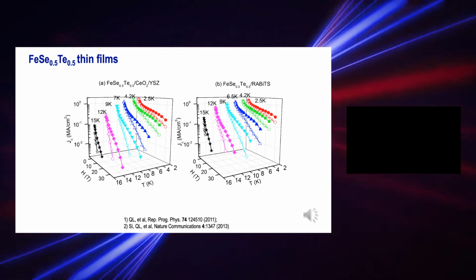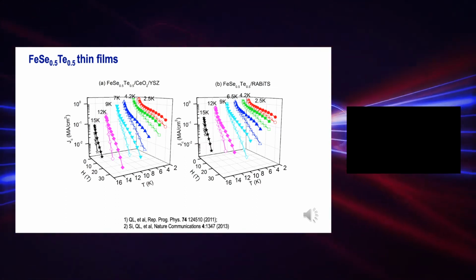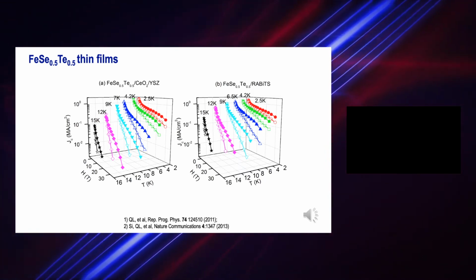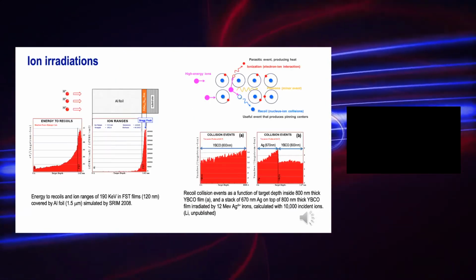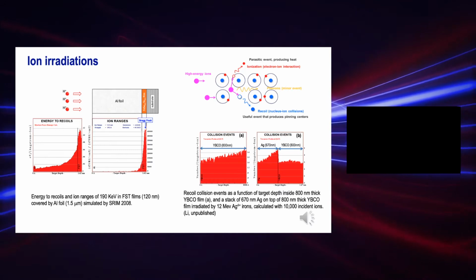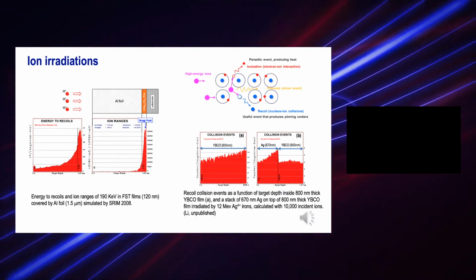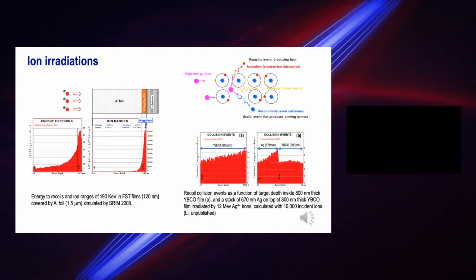And the in-field performance is very good too, extended all the way to 30 Tesla and lower temperature. Now from this, we argue that iron chalcogenide superconducting films can be usable for applications such as high field magnets. To further enhance the critical current density in these iron chalcogenide films, we look for other artificial pinning centers.